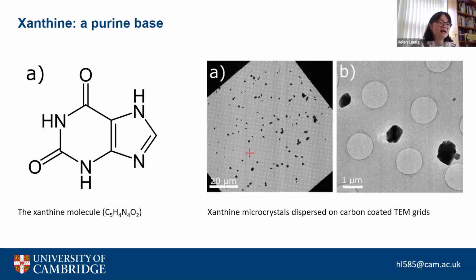So we dispersed our xanthine microcrystals, synthetic xanthine that we just purchased from Sigma Aldrich, onto carbon-coated TEM grids. And you can see on the figure on the right in panel A that dispersion is what we were aiming for, because that's the ideal separation between microcrystals, which means you can get a full rotational range without other crystals coming into view, and they're nicely separated.